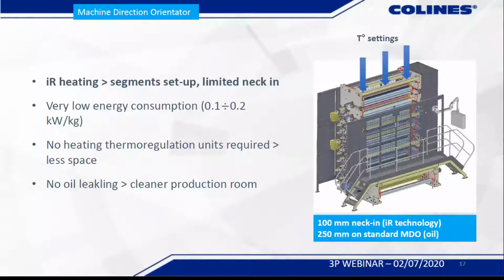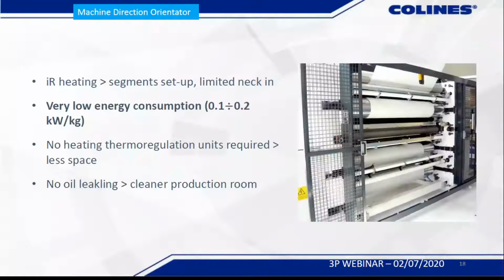neck-in after stretching. It grants a very low energy consumption, really very, very low, because we don't have any heaters anymore, any pump to push the oil around the circuit. And it's very, let's say, stable in the consumption, because the preheating or the target settings are reached, because the machine has temperature sensors on the film and temperature sensors inside the cylinders.